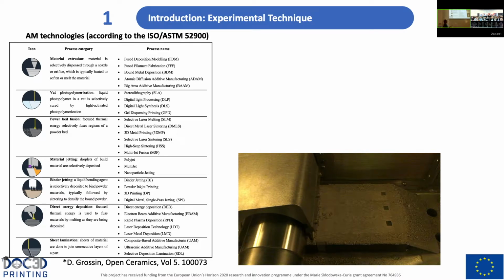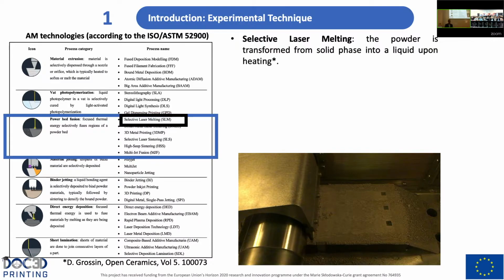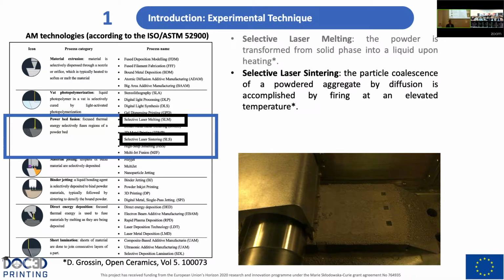Here we can see a table with all the techniques according to the standard of additive manufacturing. This presentation is focused on powder bed fusion methods, and within all the techniques in powder bed fusion, the technique that we're using in this work is both called selective laser melting and selective laser sintering. But actually the principle is different. In selective laser melting, the powder is transferred from solid phase into liquid completely. And on the other hand, in selective laser sintering, the particle coalescence, the powder aggregate by diffusion, is accomplished by firing at an elevated temperature.